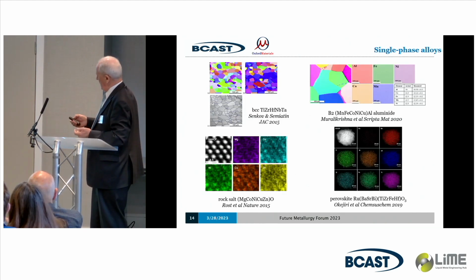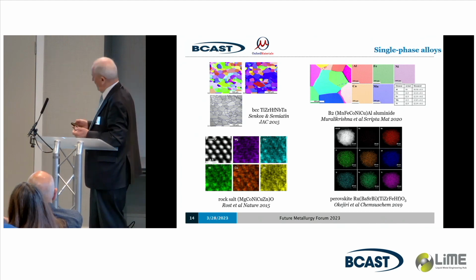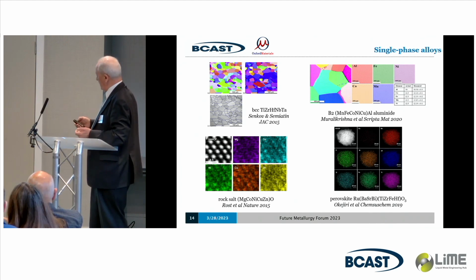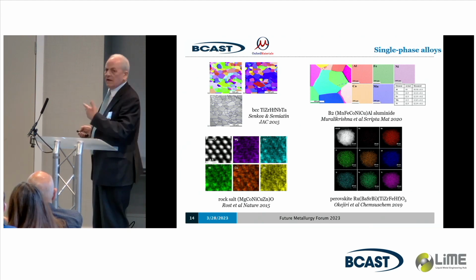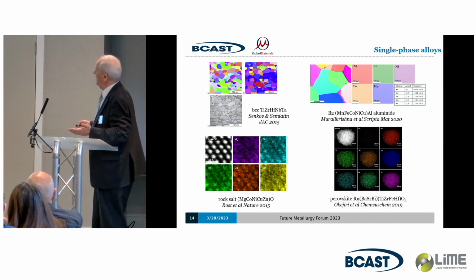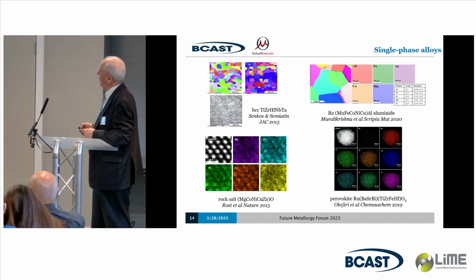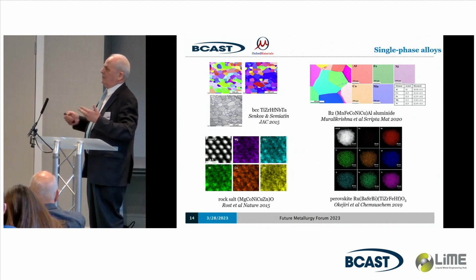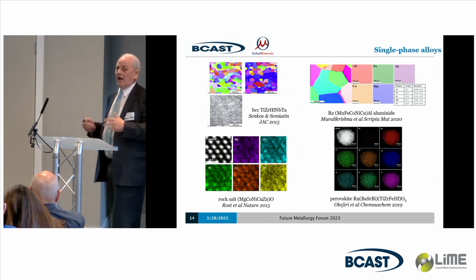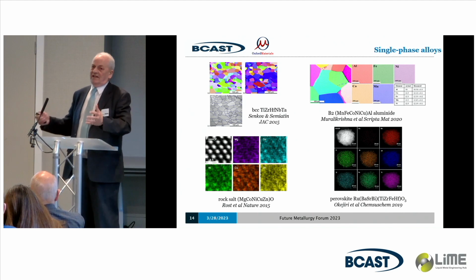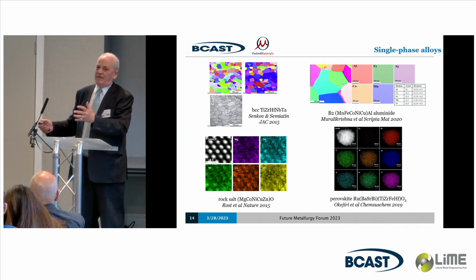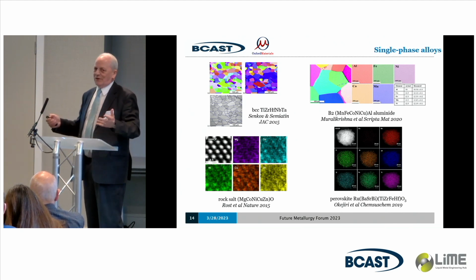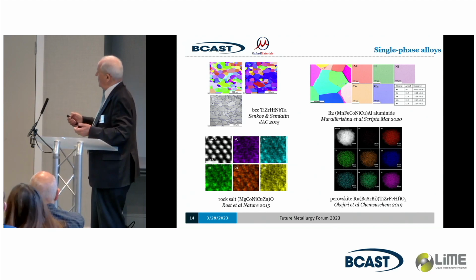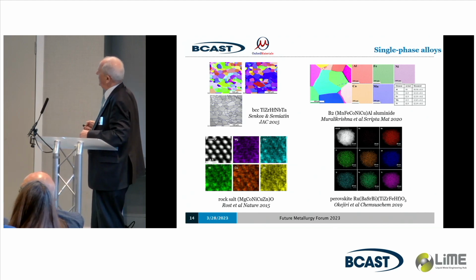Here's a picture of some of the other ones. It turns out the same thing happens with BCC. There's an enormous range of BCC alloys, which are mostly early transition metal rather than the late transition metal Cantor alloys. These are called Senkov alloys. The first one was vanadium, niobium, molybdenum, tantalum, tungsten. 5 got stuck in the scientists' imagination as we have to use 5. I don't know why. There's nothing wrong with 6 or 7. But anyway, people mostly make 5, as you'll see in a second.